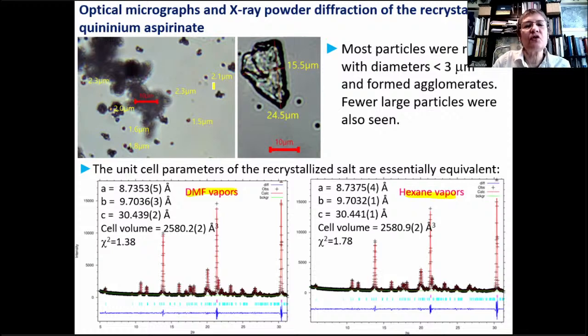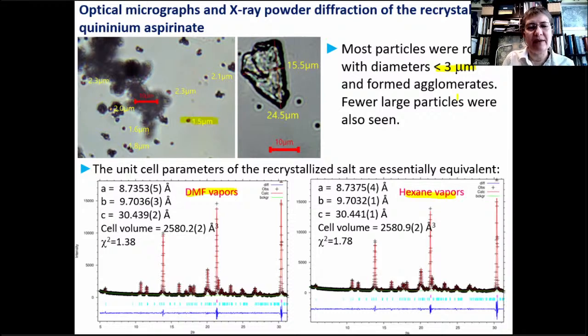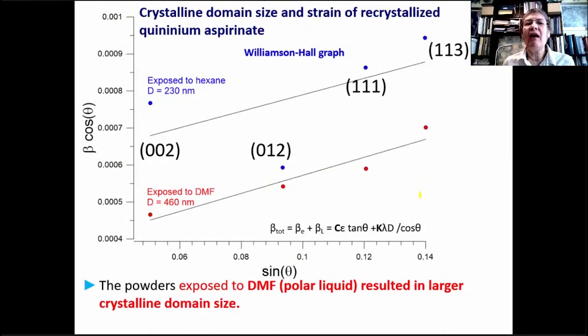So under the optical microscope, most of the particles are still less than 3 micrometers in size, and they are kind of round in shape. And a few particles of larger sizes are observed, but these are really few. The majority of them are these small micrometer size particles. So what happened with the crystallinity of these two powders that were recrystallized with hexane and dimethylformamide? So we did a Williamson-Hall graph, whose result gives the parameters indicating the crystalline domain size and the strain of those particles of the recrystallized powders.